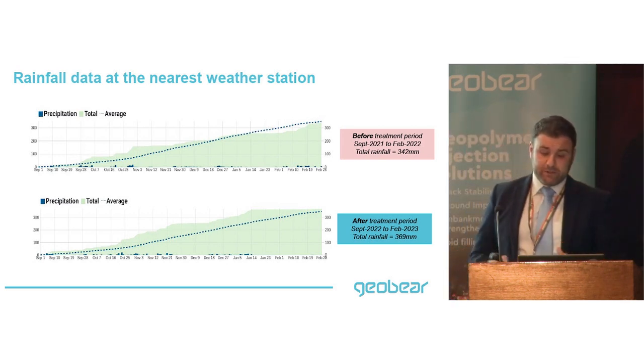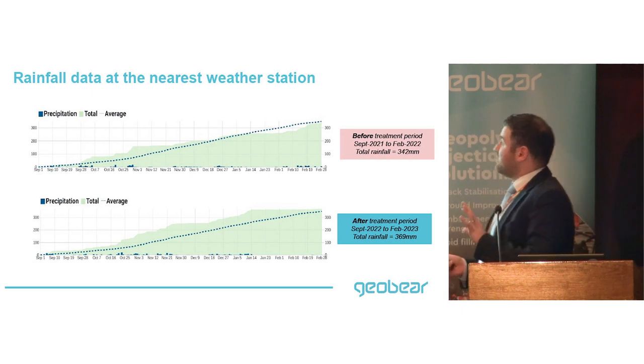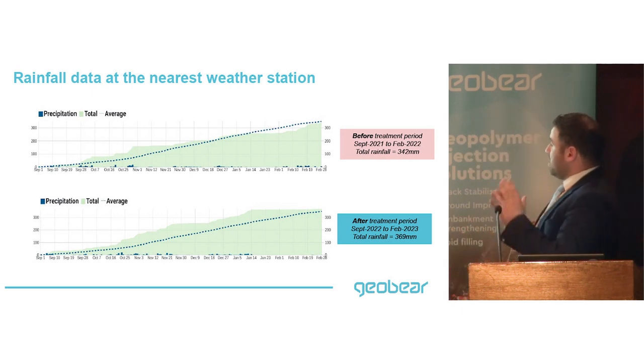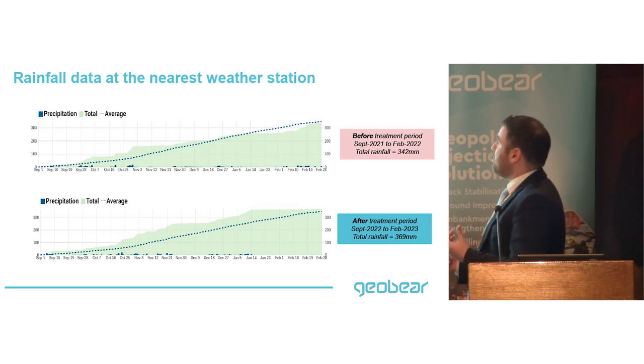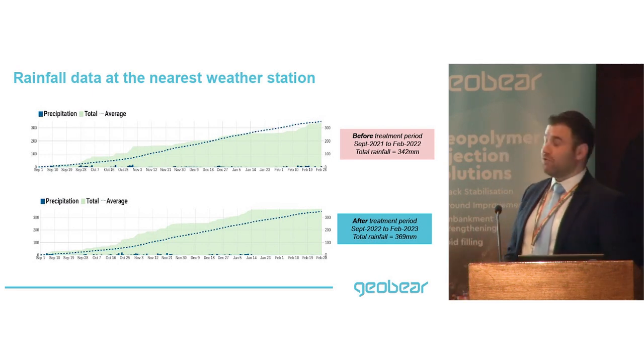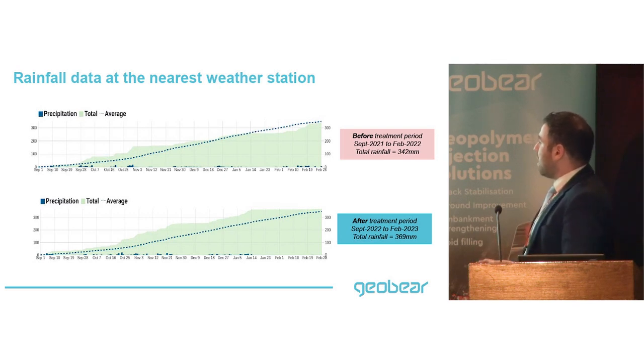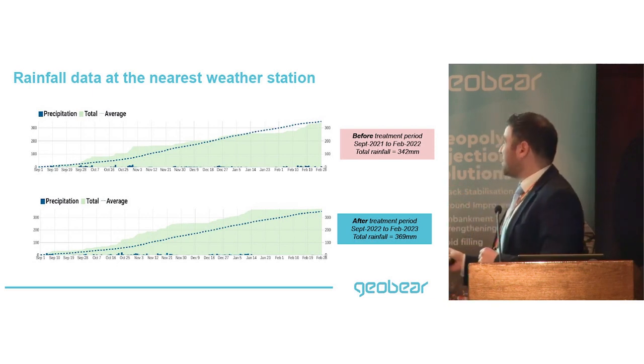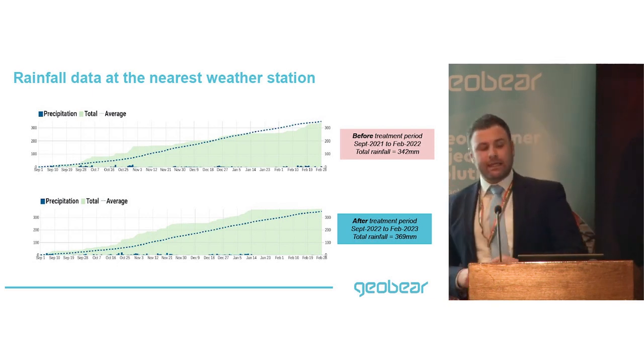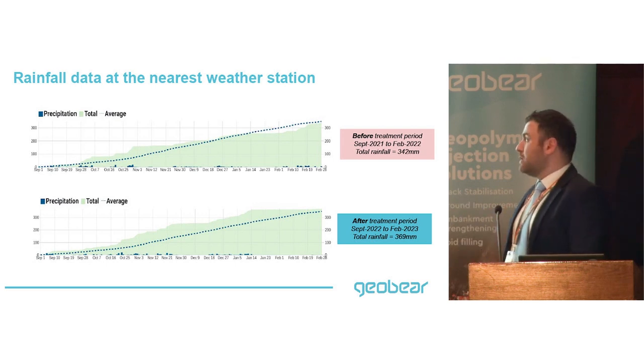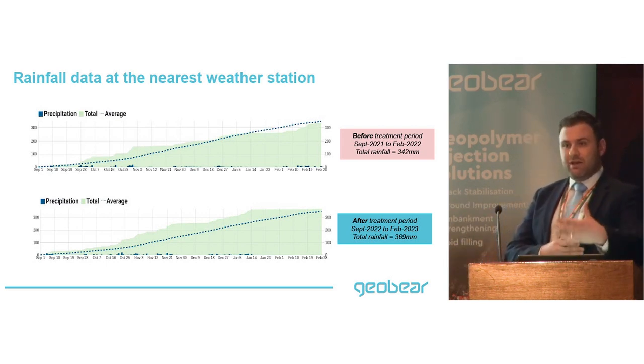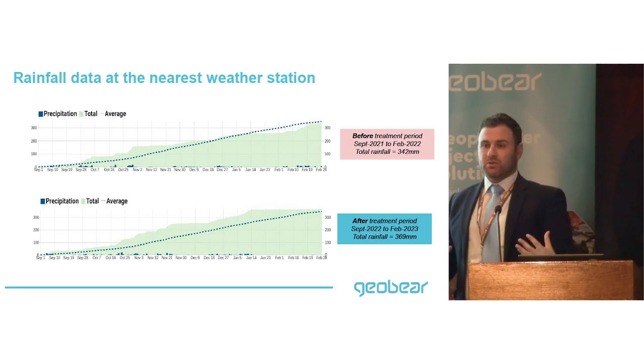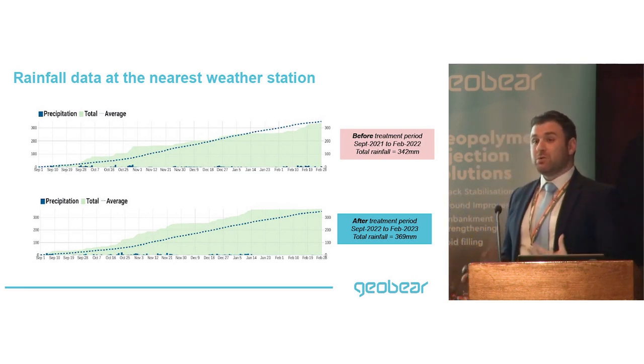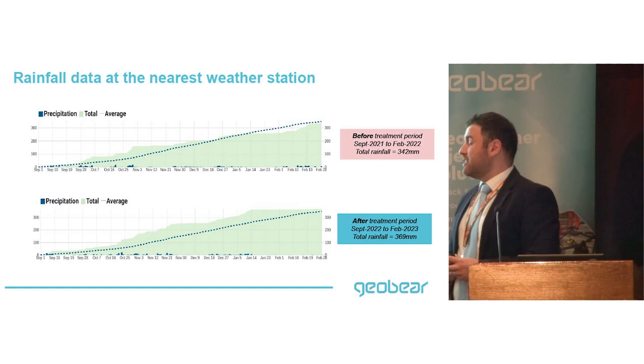Well, I've compared the rainfall data in those two periods at the same location. Before the treatment, between September 2021 and February 2022, the total cumulative rainfall was around 342 millimeters. After the treatment, I took exactly the same period and compared the total cumulative rainfall, and it was actually higher—slightly rainier after the treatment. So that tells me water was not really a factor in why we were seeing this improvement. It wasn't because it was drier; actually it was slightly wetter than anything.